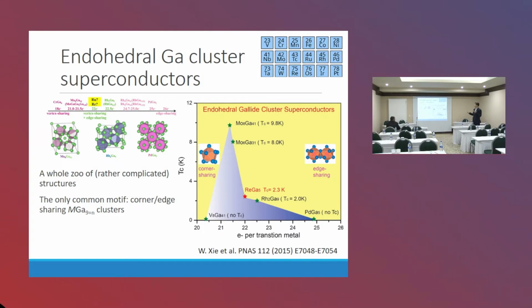It's a monster, but they can be kind of put in one context by plotting the Tc versus some electron count. Because they share some common motif, some common electronic structure motif, which is the corner or edge sharing transition metal centered gallium-9 or gallium-10 clusters.